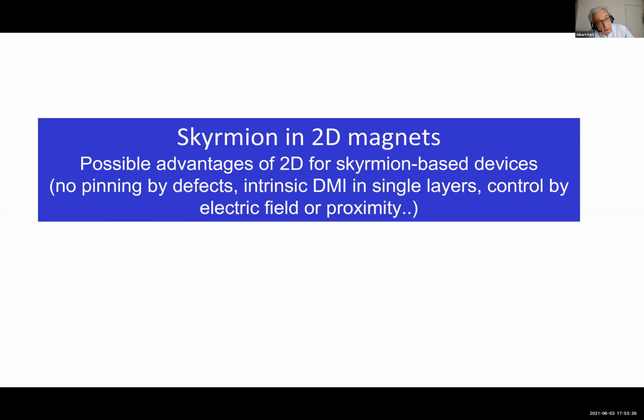So one of the possibilities with 2D materials, with this very pure layer of FGT, for example, or other 2D magnets, is to escape from the problem of the pinning by defects and to obtain more uniform velocity of all the skyrmions in the same layer. And this is a difficulty, for example, in some applications: one needs to move skyrmions with the same velocity and to avoid pinning of some of them by defects.